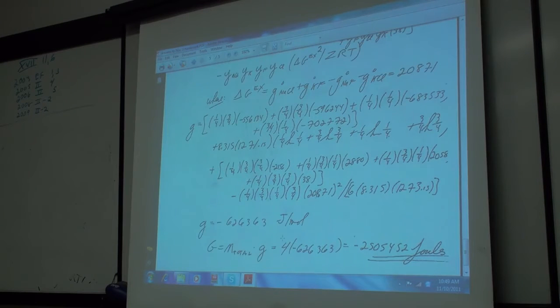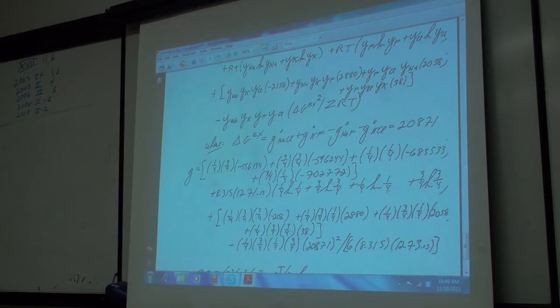Okay. The point here is mainly, I suppose, making the substitutions. These terms, maybe be sure that you understand where these terms come from. This is Y sodium. In the sodium chloride KCl system, Y chlorine will be 1, and this is the excess Gibbs energy of mixing in the sodium chloride potassium chloride system, multiplied by Y chlorine, which is less than 1 as you get off into the ternary system.